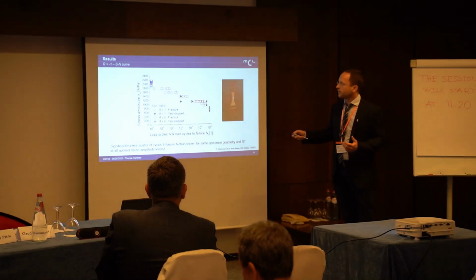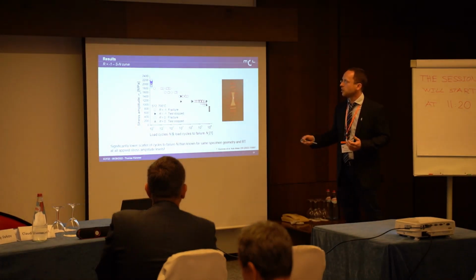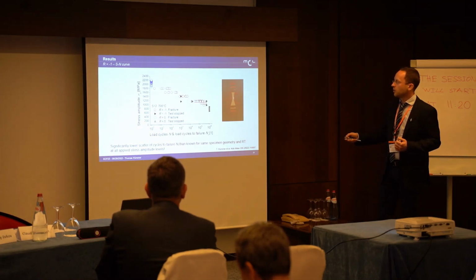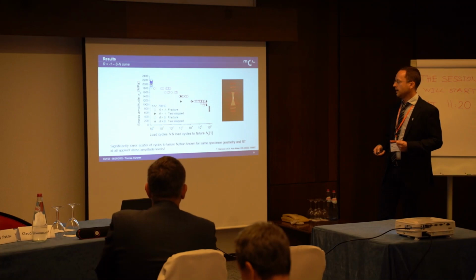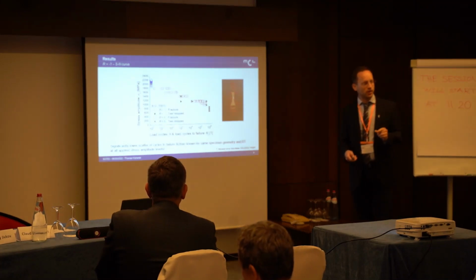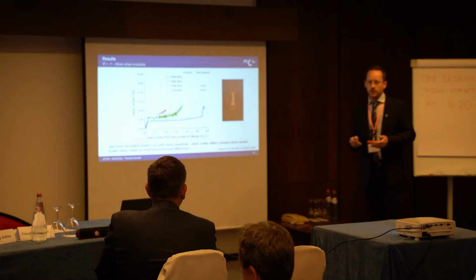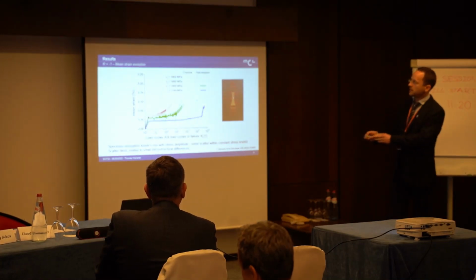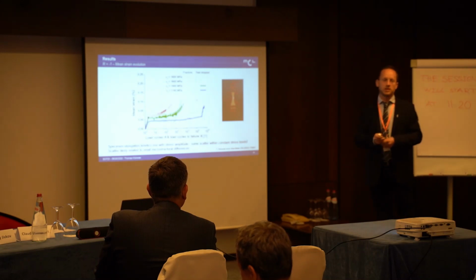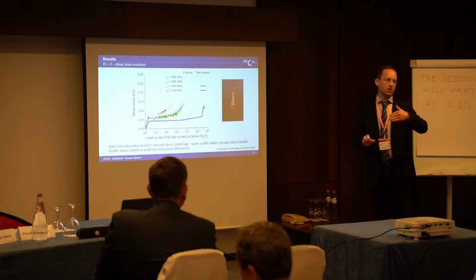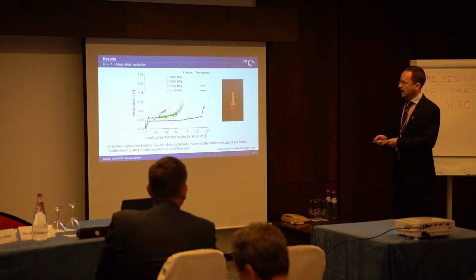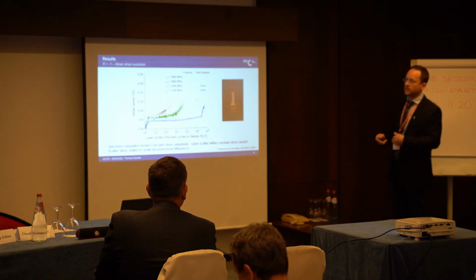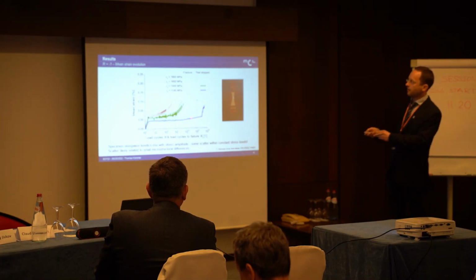You see here again the R=-1 loading and R=0 loading case distribution, and then what you also see if you look at the SN curve, so to say, is that it's a rather low scatter, which is also very uncommon for this kind of large specimens in this class of material. But it's also interesting, I didn't bring the stress-strain hysteresis curves for you, but please look at the mean strain and think of it as an elongation of the specimens that happens when these cavities accumulate and don't fully close until the compressive half cycle, as Pichler has proposed. And you see the kinetics of these mean strain shifts, so to say, are higher for higher stresses.